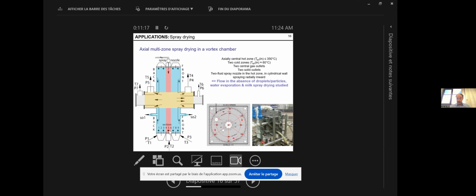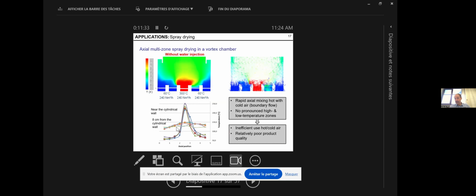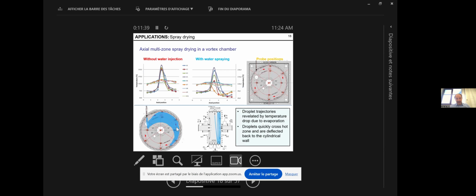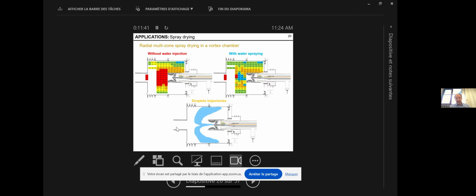Two problems. The central zone we could not keep hot enough, and these zones where we were supposed to have mild temperature conditions to do final drying and avoid stickiness, they were too hot. So we had to change the concept. And so this is shown here. These are temperature measurements. You can see what the problem is. So we had to change the concept and went to the radial multi-zone dryer.